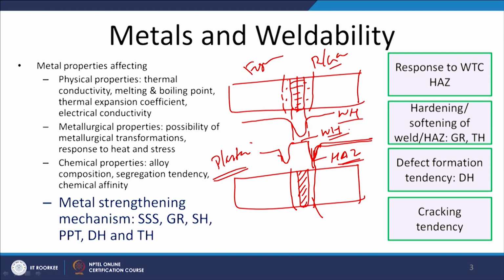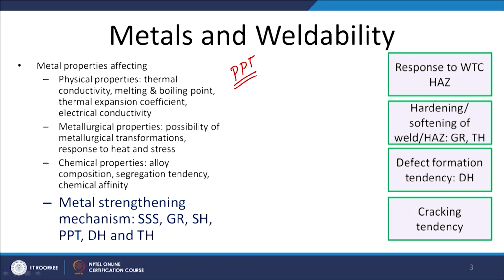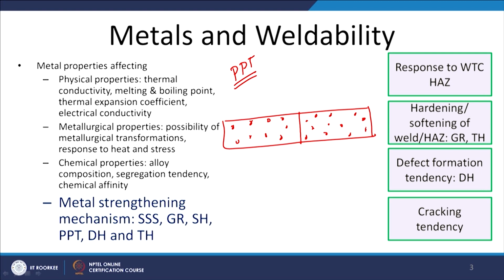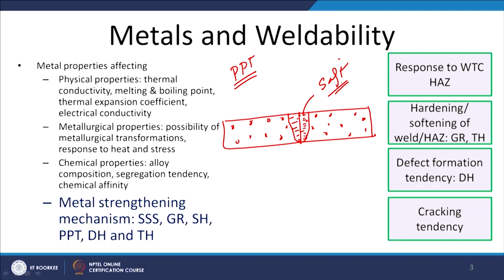Then lastly we will be talking about the metals strengthened by precipitation hardening. Like say these are the two metals, both designed to be strengthened by formation of suitable precipitates like this. Now when these are subjected to fusion welding, all these precipitates will be brought to the molten state and they will get dissolved, and certainly the conditions are not favorable for their formation again during solidification. So in any case the weld zone will be softer in case of the precipitation strengthened materials.